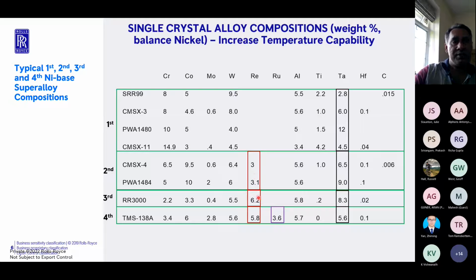Then you go to third generation alloys. Again, the only difference between them and second generation alloys is an increasing amount of rhenium. So going from about 3% rhenium to about 6% rhenium. So third generation alloys, again, the reason for going from second to third is because you want to have stronger alloys. You want alloys which are more capable of resisting creep, specifically in parts of the turbine, like the IP blade, which you don't generally cool. So those blades are generally hotter because the metal is running at a higher temperature, and therefore you want the blade not to have poor creep properties. So one of the main reasons for adding an increased amount of rhenium is effectively to increase the creep strength.